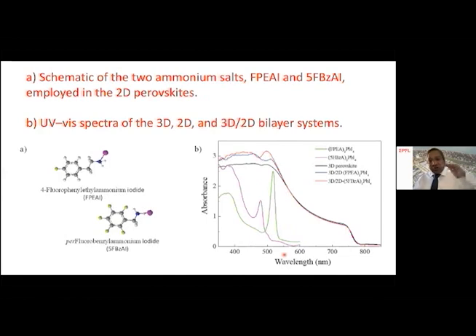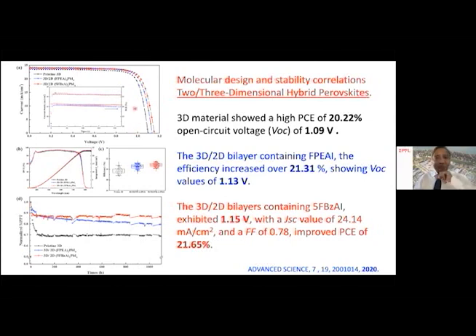Similarly, we have deposited on top of a three-dimensional perovskite. The black one is the reference sample. The blue one is with the fluorophenylethylamine cation two-dimensional perovskite, and the red one is pentafluoro. So instead of going through all the characterization details, let me go directly to the solar cell efficiency data shown here. Take the reference sample, that's 1.09 volt, just focus on the VOC. Using fluorophenylethylamine, we increased VOC from 1.09 to 1.13, that's the blue line. And the power conversion efficiency went up from 20.22 to 21.31.